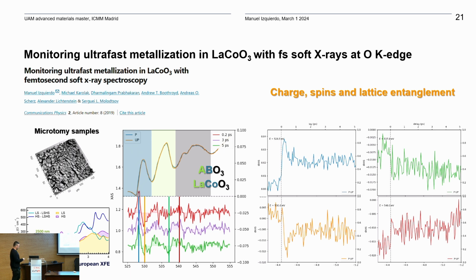So, in this case, the idea that I had was to use the sample preparation technique that biologists use to prepare bio objects. Basically, they cut with a microtome, and you can see here these microcrystals of LCO with a maximum thickness of 100 nanometers that we used with this transmission to do time-resolved absorption spectroscopy.